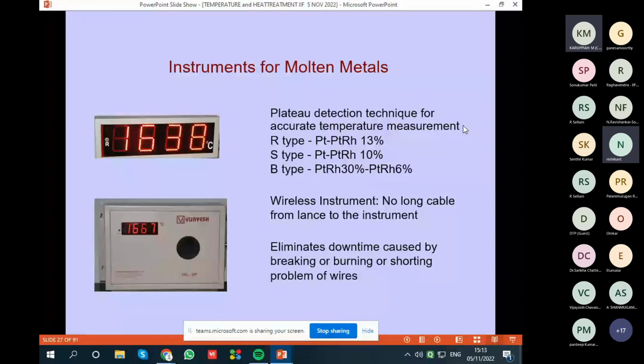There are different types available, R, S, B. I will strongly recommend to use R-type, which is 13%, rather than S-type, because R-type gives you more resolution, more output from the thermocouple than the S-type. And if you are measuring temperature above 1600 degrees centigrade, then only you have to go for B-type, which is generally recommended for 1600 to 1850 or so. Otherwise, R-type is most suitable for most of the foundries.